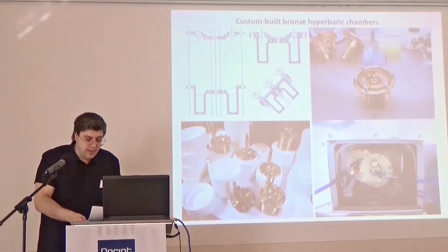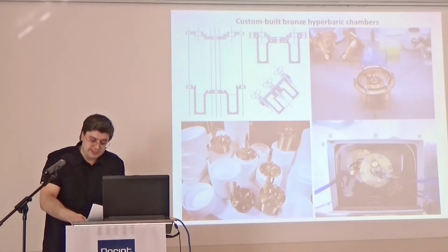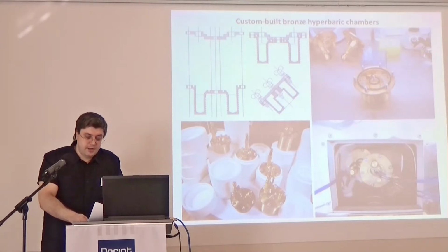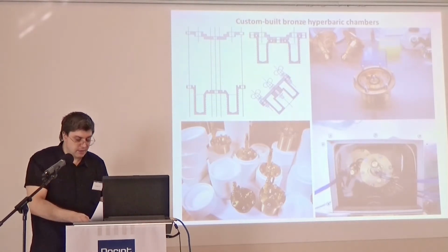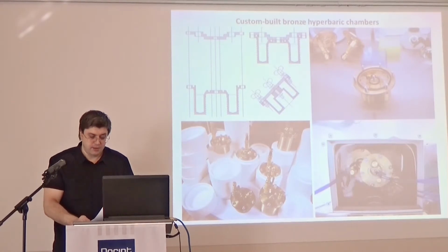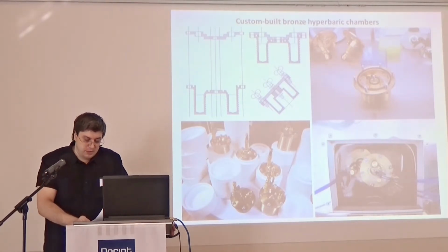Yeast survival at all xenon pressures tested, from 3 to 7 bar, after 2 hours of pressure chamber exposure at minus 20 degrees with subsequent chamber immersion in liquid nitrogen, 68.5 plus or minus 6%, turned out to be better than in control, 35 plus or minus 6%, and comparable or even higher to that of 5% glycerol application, 50 plus or minus 25%.